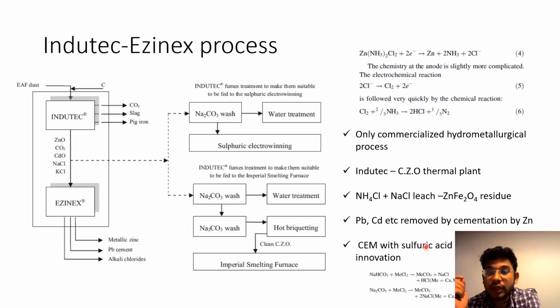How did chlorine not migrate to the anode side? How did chlorine evolution not happen? 2 things. First, the chlorides were stopped by using a cation exchange membrane. In a cation exchange membrane, only cations can go through. Chloride is an anion. Okay. Second step, what they did was also fill the other compartment with a non-chloride solvent or solution. They use sulfuric acid. Easy to produce oxygen from there.